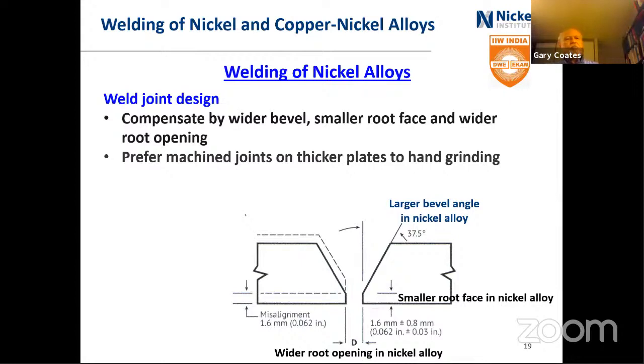Now, machined joints are preferred on thicker plates to hand grinding. Grinding, whether it's stainless steel or nickel alloys, is not a great job. It's hard to do, hard to control, so you don't get a uniform joint preparation. For the welder's sake, because these are expensive materials and a little more tricky to weld, you really should have as uniform a weld joint as possible, and that's often done through machining of the material rather than hand grinding.